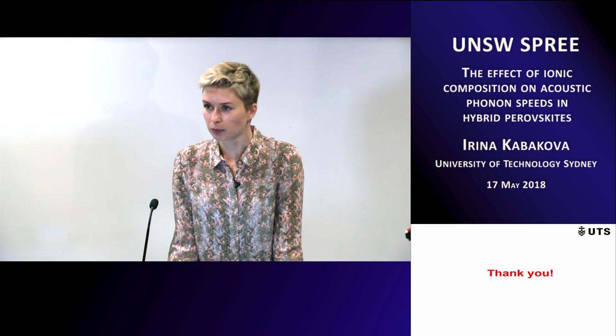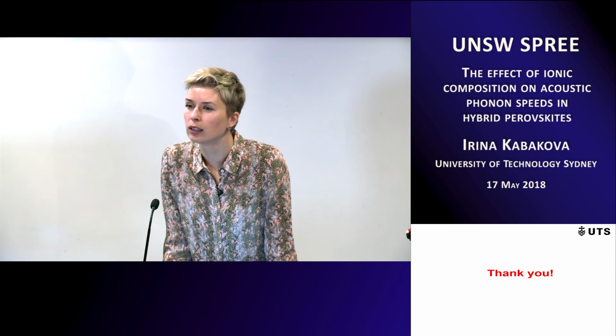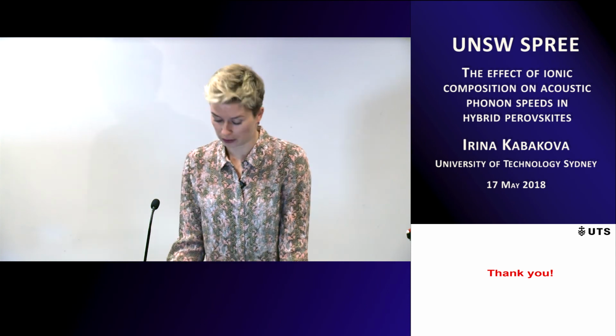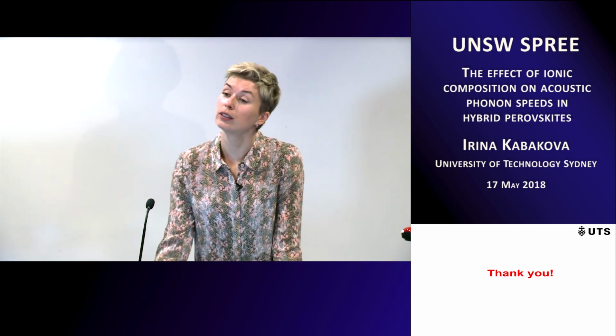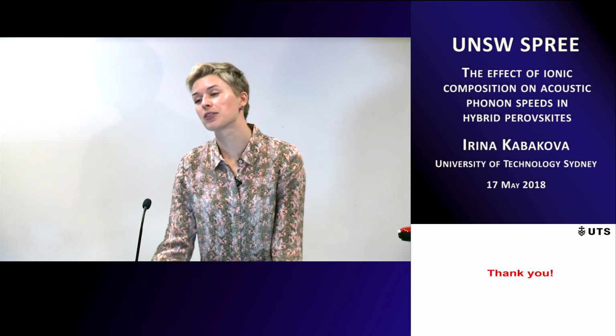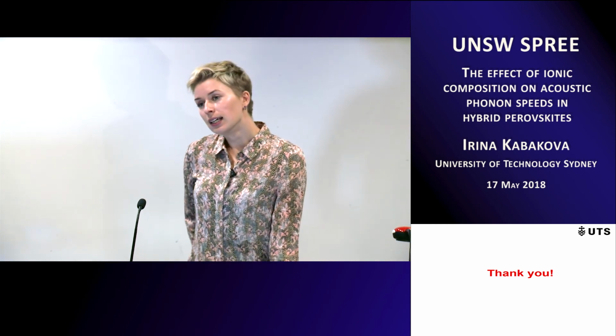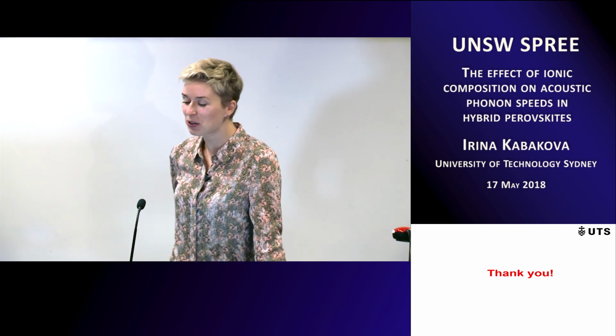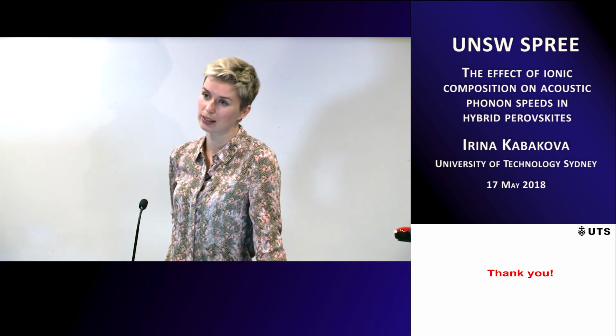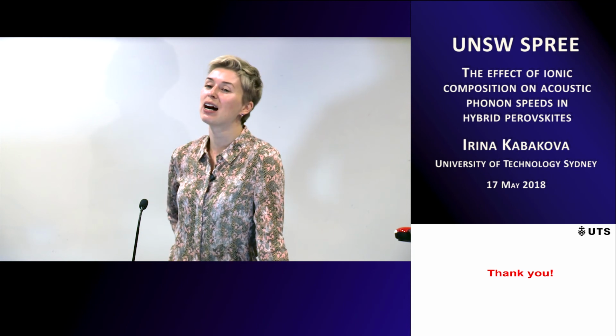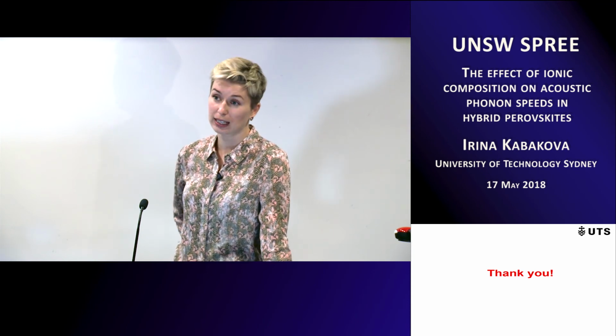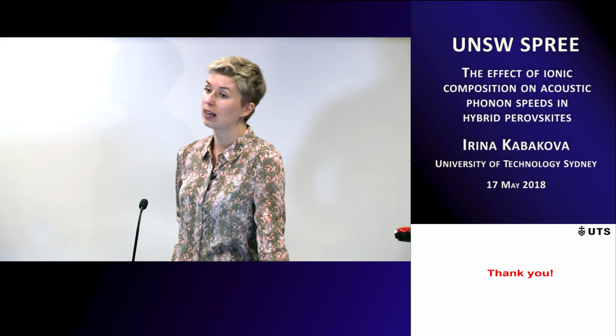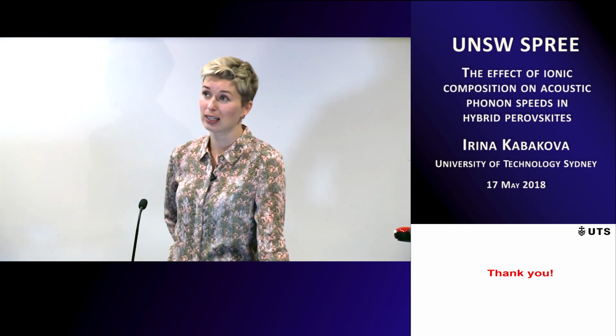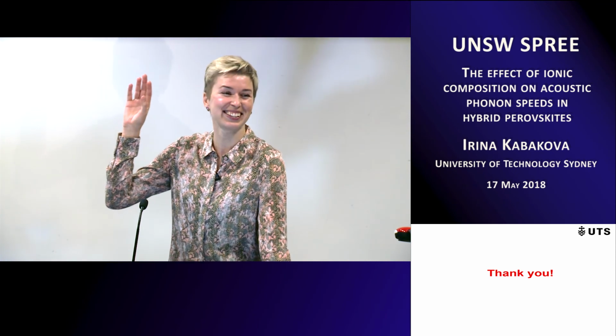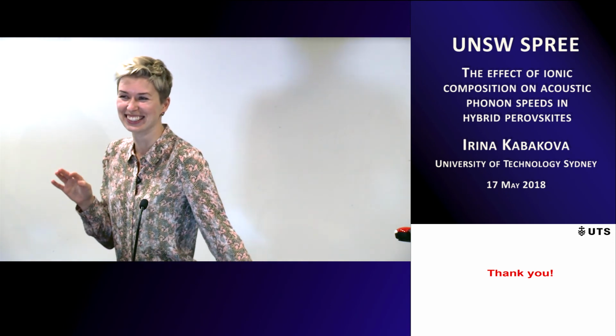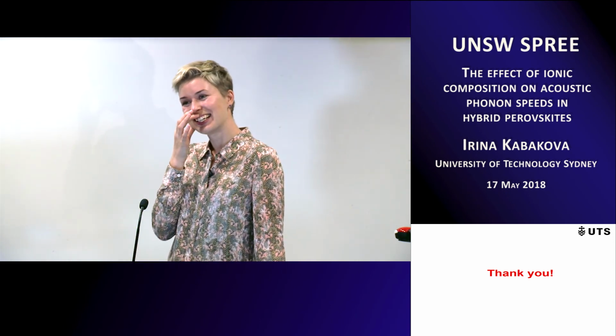I noticed you haven't done the measurement on iodide perovskite. Iodide perovskite. So you only have... Yes, that's right. Is it because it's not cubic at room temperature? No, the answer is very simple. We actually did have these crystals, but we couldn't measure them. They were absorbing at 670, so essentially they were steaming. They were absorbing everything.